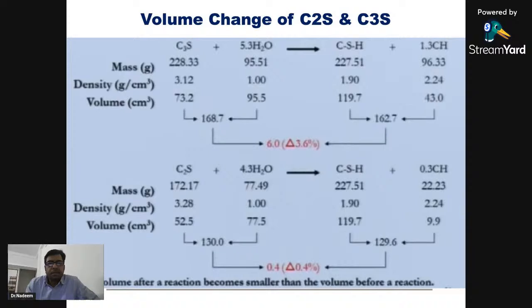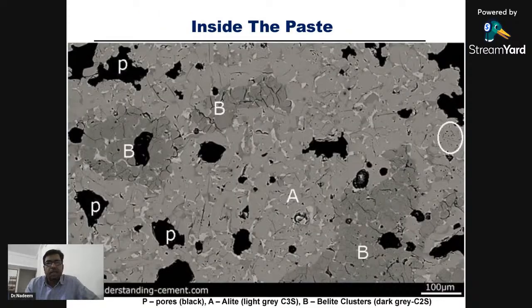Coming to dicalcium silicate, which is reacting with water, forming CSH and a byproduct in the form of calcium hydroxide. Again, there is a delta of 0.4%. Now both these deltas are nothing but porosity being created in the concrete. So if you again see our concrete structure at a micro level, you will find B is belite, dicalcium silicate, A is alite, and P, this black part, is pores. Whatever reduction in content is happening, in the form of evaporation of the water, remains in the structure in the form of pores.